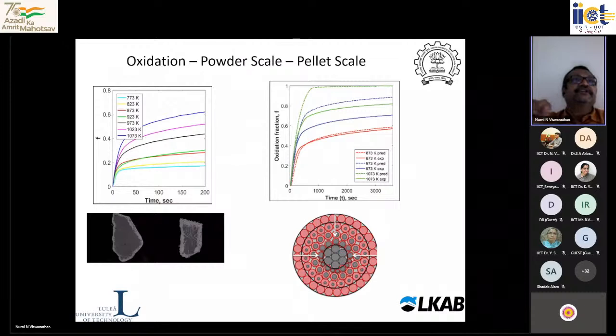Similarly, when it comes to oxidation, again we did experiments at two scales. This shows a single magnetite crystallite or particle, powder scale, and how the oxidation takes place. You can see the needles which are growing in, basically Fe3O4 becoming Fe2O3. So there is a kinetics involved in this. So one needs to study the kinetics at this scale, and there are models available. For this kinetics we found there is a well-known model called the Avrami model, which is used in phase transformation, and that model fits very nicely for this magnetite to hematite.